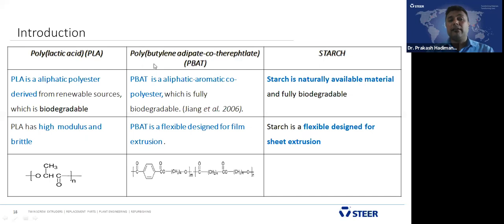In this case study, we have used PLA, polylactic acid. The second one is polybutylene adipate co-terephthalate, PBAT, and the last one is starch. We use 3 materials. PLA is an aliphatic polyester derived from renewable sources, and is biodegradable. Again, PLA has higher modulus but is brittle in nature. It is difficult to get flexibility. Elongation is lower in PLA.